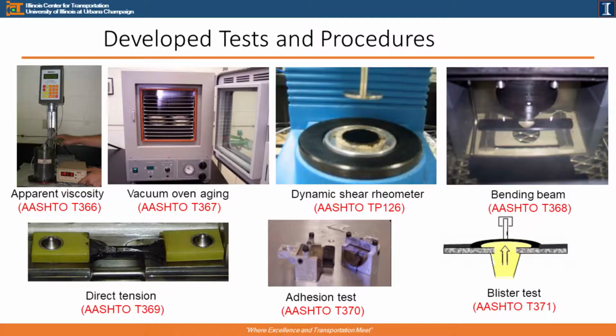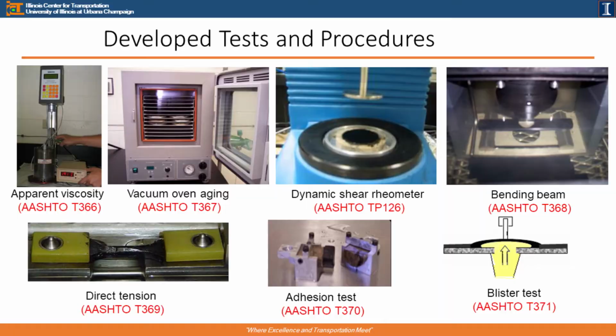And also, however, they use the tension test. As you know, for the asphalt binder, we started with the direct tension test, but later we dropped it. But in this case, they put it back for this silicone characterization. And then they have developed two different testers, the adhesion test and the Blister test. As you can find in the red number, every test is already standardized in AASHTO. So you may refer to all those individual tests.